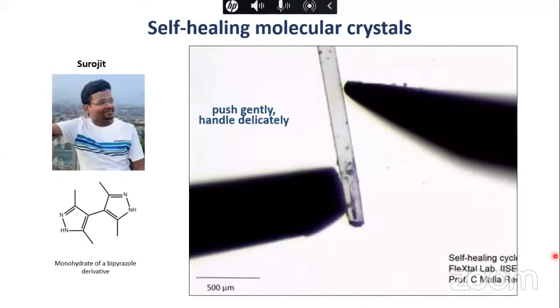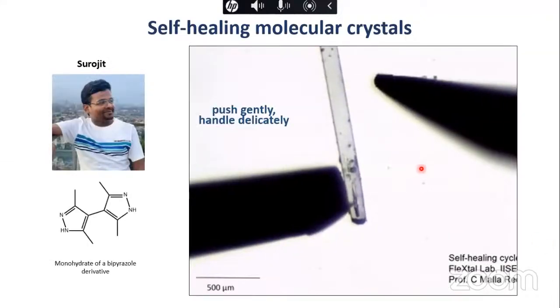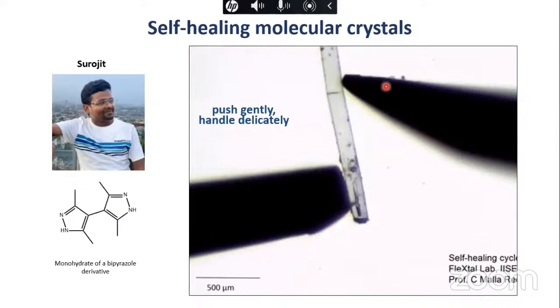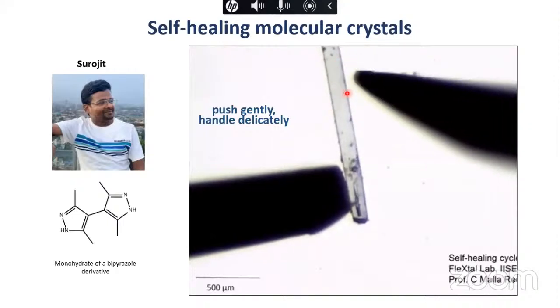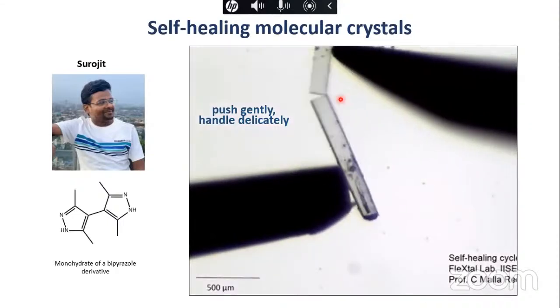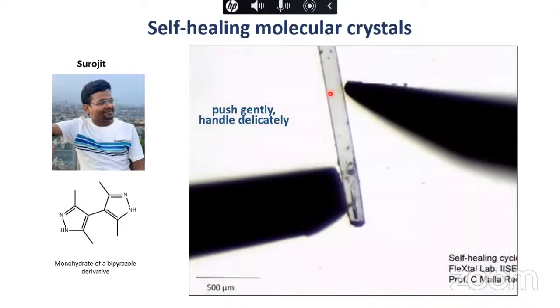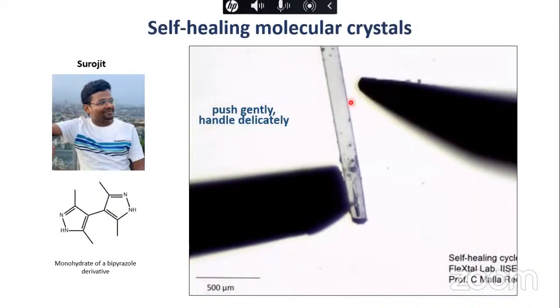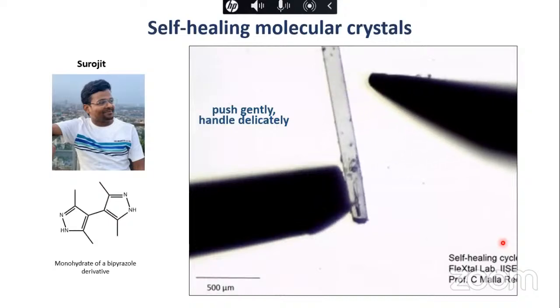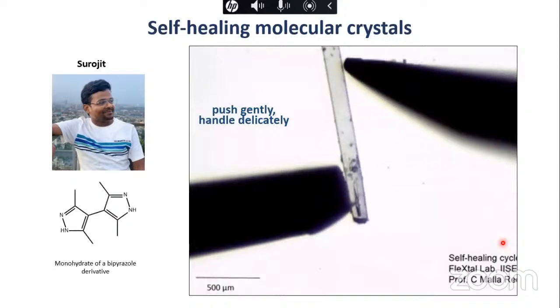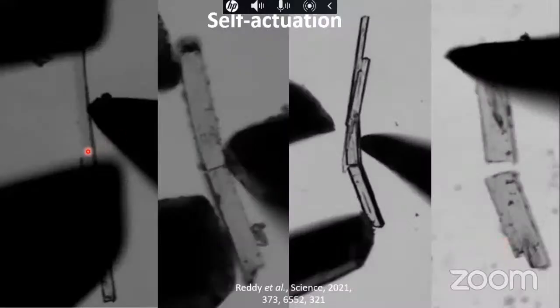But when he looked at these crystals under very small force, like when he just pushes the crystal, as you can see here, it develops a crack, and then these cracks disappear on their own. For example, if you look here, the crack is totally gone. We were very surprised, because normally in organic crystals you don't see anything like that.